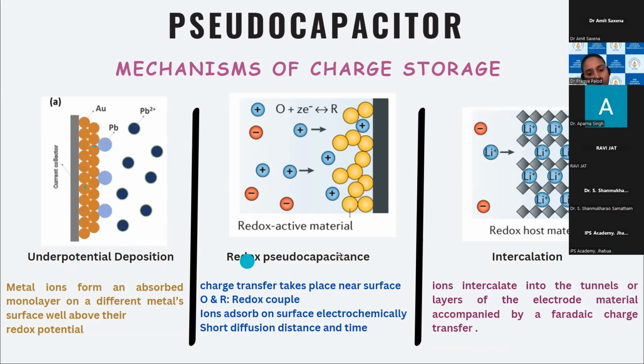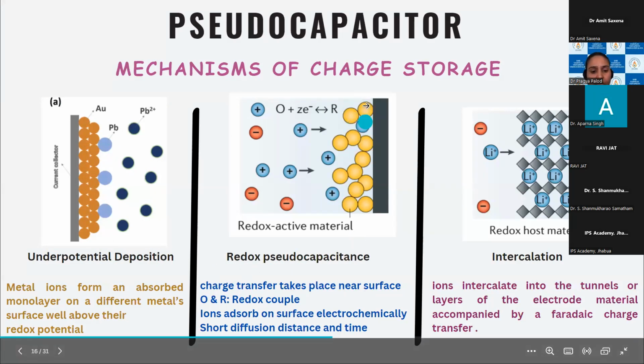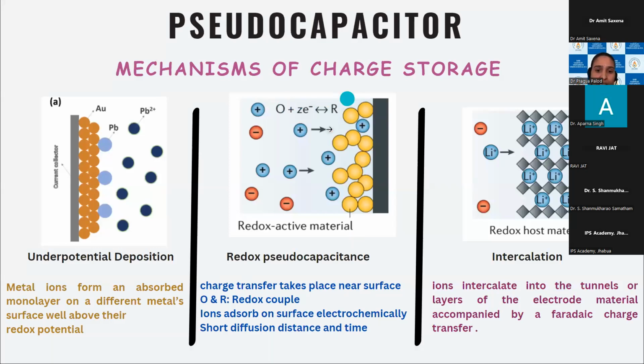Now in case of this redox pseudo capacitance, charge transfer takes place near the surface of the electrode, and here in this reaction O and R denote basically the oxidized and reduced form of the redox, and ions adsorb on the surface electrochemically. Since short diffusion distances are active, therefore the process also takes place in a short span of time. Now another kind of mechanism for charge storage is intercalation. Intercalation is the insertion of ions into the tunnels of the layers of electrode materials, and that takes place by a Faradaic charge transfer. So the redox host materials of fibrous kind of nature prefer this kind of intercalation, because they have wide gaps for the ions to get inserted in channels.